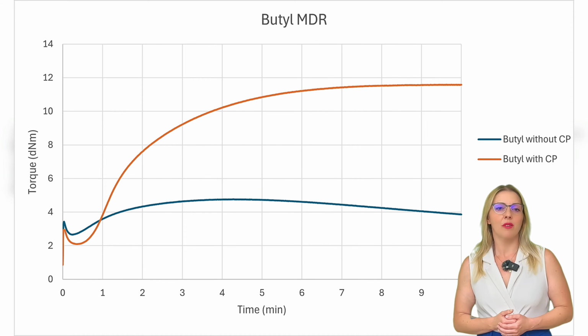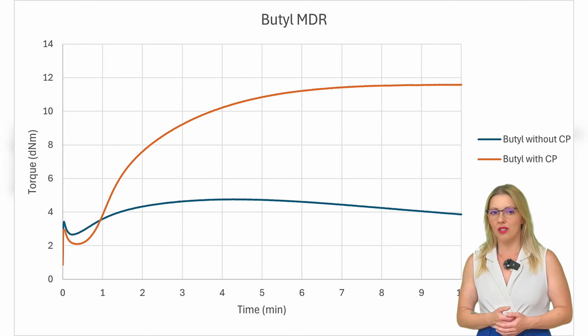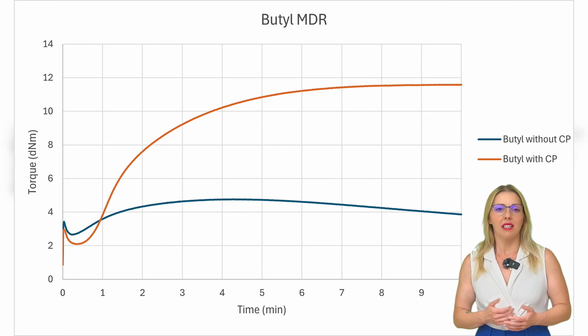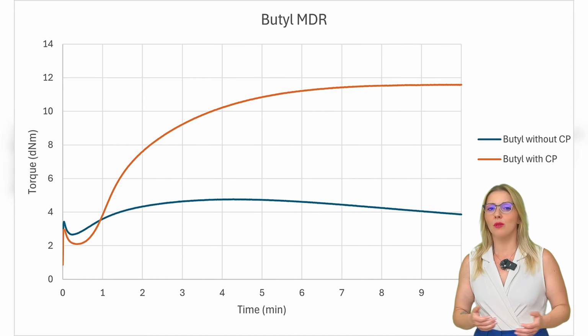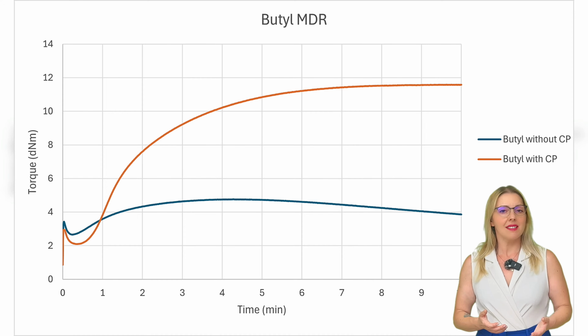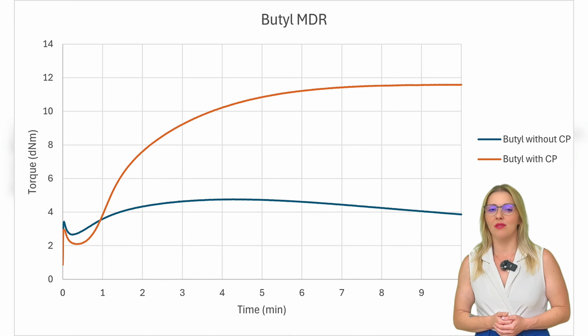Once I added the sulfur-based curing system, the orange curve shows a strong increase in torque. The cure develops quickly and plateaus smoothly, indicating a well-formed crosslink network. This is exactly what you want to see in a revulcanized rubber. Evidence that the network can be rebuilt using standard curing chemistry.